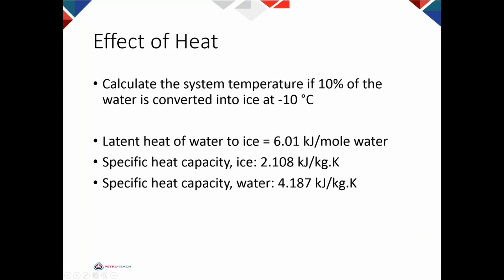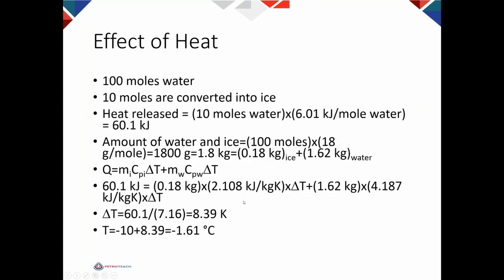I assume water at -10 degrees, and assume that 10% of this water becomes ice. I want to calculate the final temperature. Relating the heat of water formation to ice, the specific heat capacity of ice, and the specific heat capacity of water, I can calculate that if 10% of water becomes ice, the temperature increases from -10 to -1.61. And that's the reason that water doesn't freeze at 0. It melts at 0 because you need to have some subcooling to start ice formation.